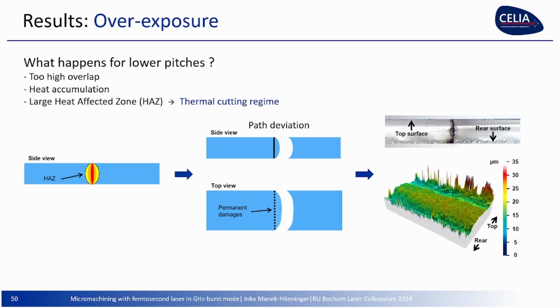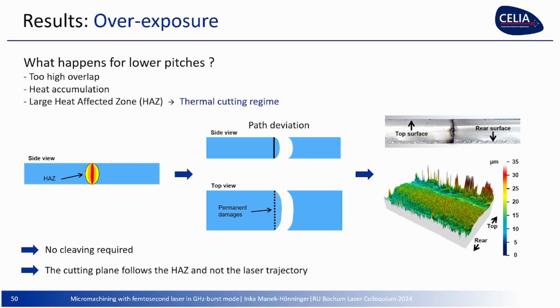So this is a regime that, usually, you have to avoid, because the good thing is you don't need any cleaving, the part falls out itself, because we are in somehow a thermal cutting regime, but the cutting plane follows the heat affected zone and not the laser trajectory, and usually it's not what you want. So there you have to be careful.